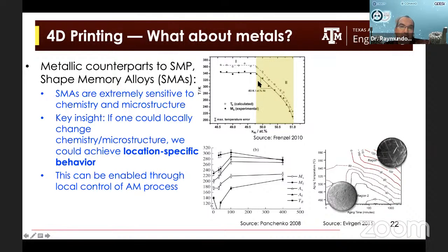There are alloys like nickel titanium hafnium where this change is like 3 or 4 times larger. You can change the transformation temperature by 500 Kelvin by changing the composition by 1 atomic percent. Okay. The same thing applies to microstructure.